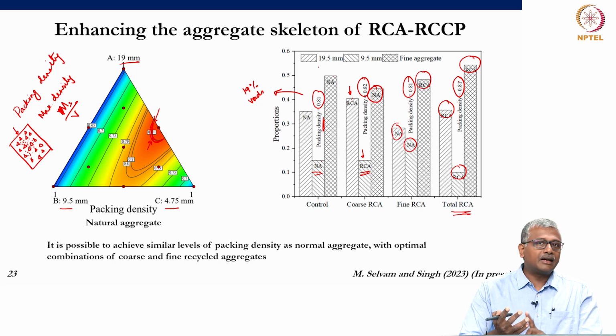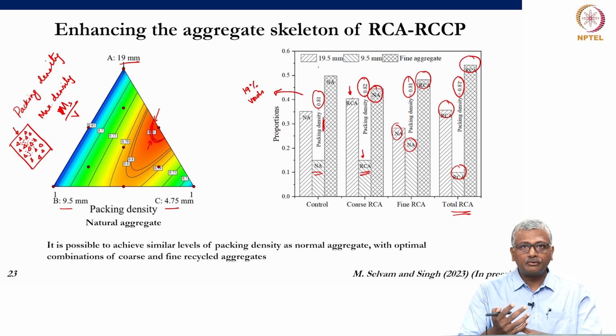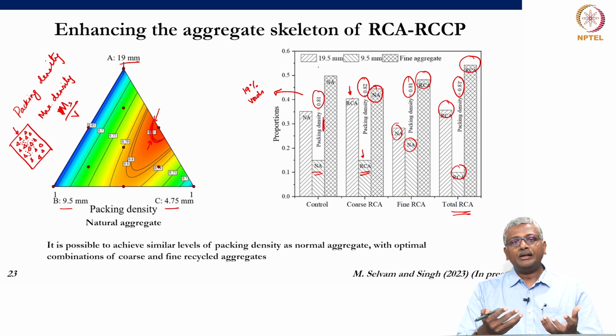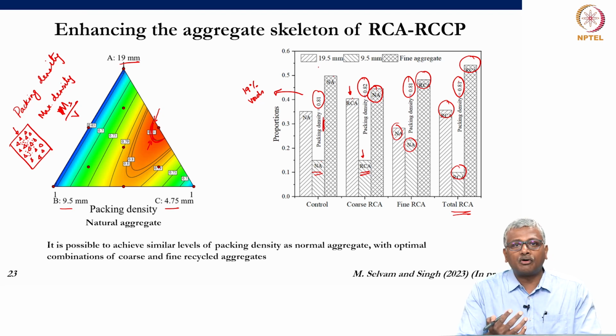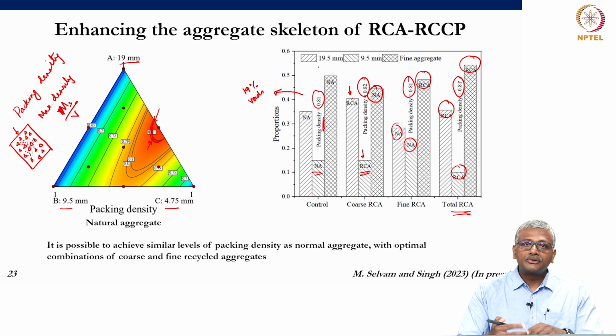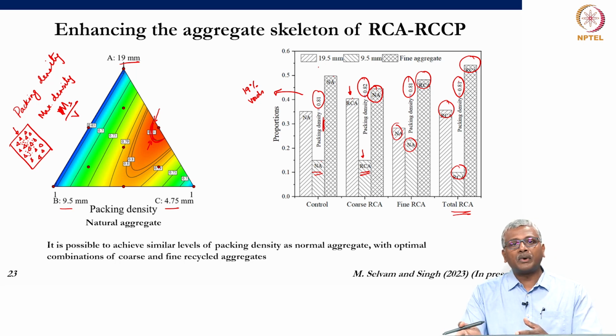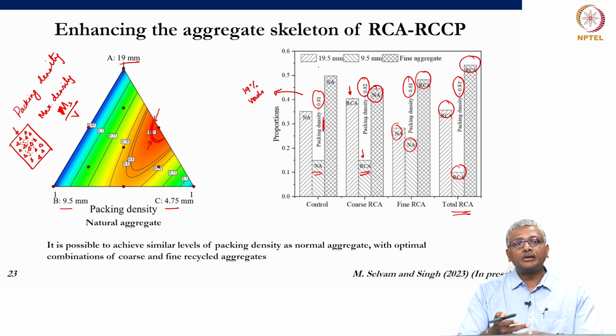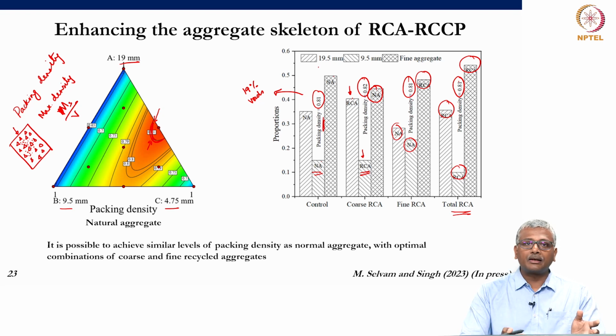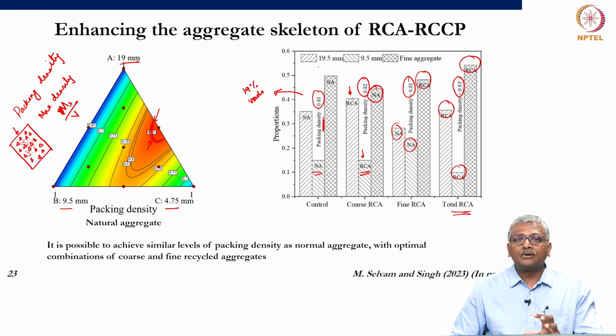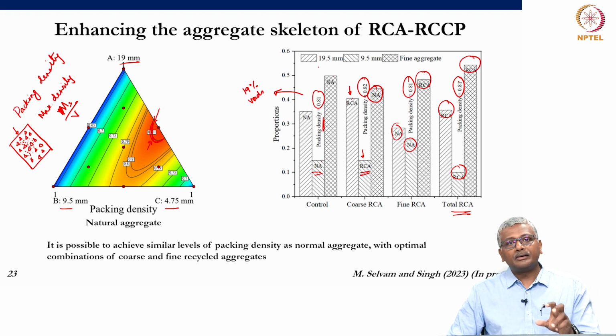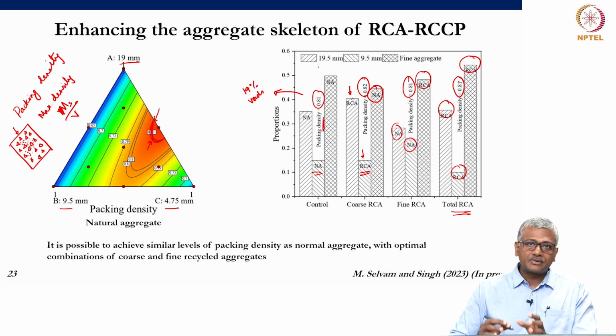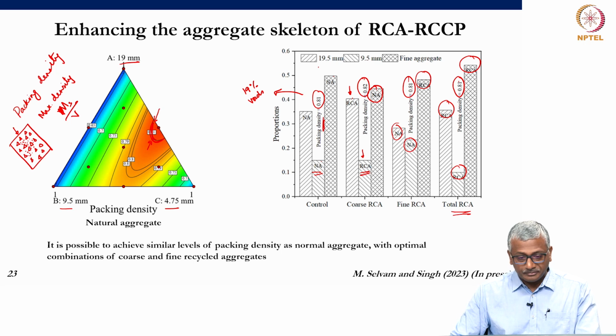So, here we are taking advantage of the fact that we do not need workability. So, we can pack in as much of aggregate as possible, but the degree of compaction is absolutely important for me to achieve because that determines my overall performance of the roller compacted concrete pavement. So, that degree of compaction through appropriate particle packing approaches, I can show that now I can use recycled concrete aggregate also to the same extent as natural aggregate by optimally designing the proportions, okay. So, it is very important for us to ascertain all the characteristics that could be altered because of the presence of recycled concrete aggregate as opposed to conventional aggregate and design appropriately.